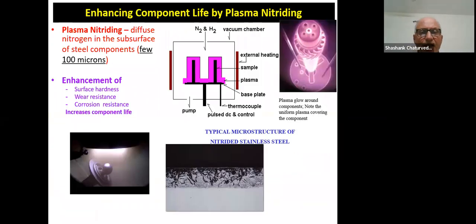Okay. Let's look at some other applications. You can increase the lifetime of industrial components using a process called plasma nitriding. Now, you're already aware of gas nitriding. The disadvantage with gas nitriding is that you have to heat the component to a certain temperature. In temperature sensitive components, that can cause distortions, they change dimensions, which are not very nice. Also, plasma nitriding gives you a higher case depth. So the overall lifetime increases. And you get very uniform case depth around the component.